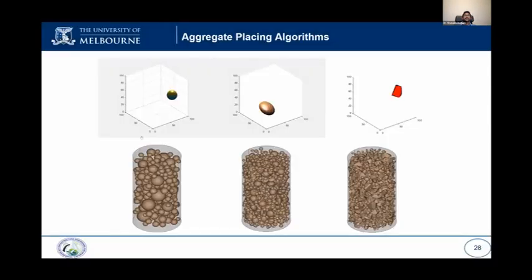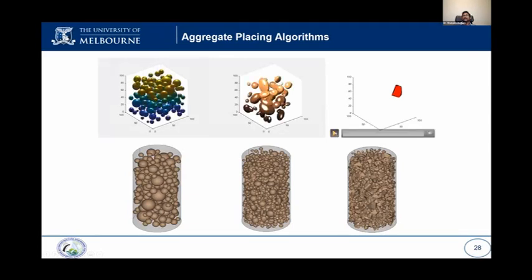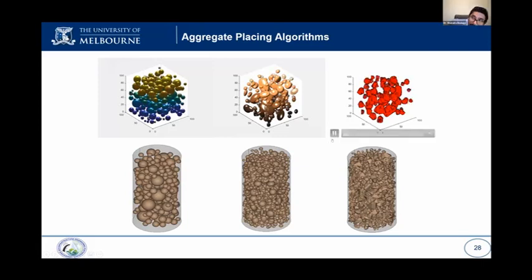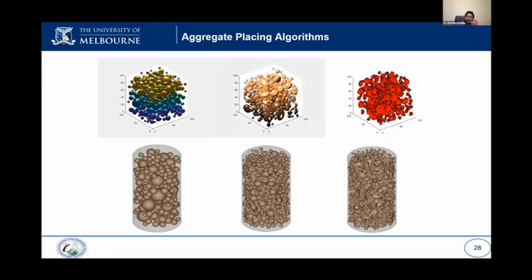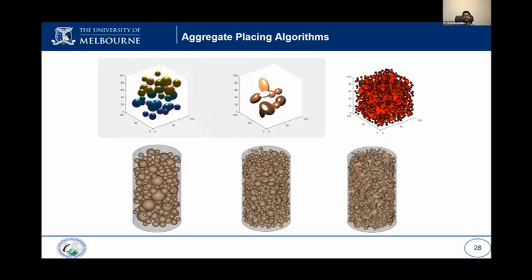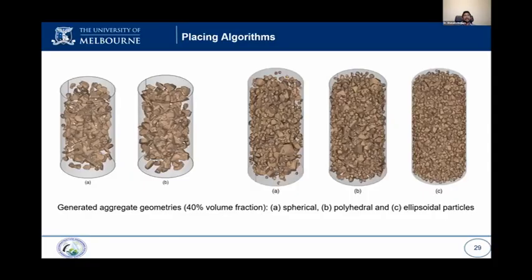So now it's about placing. I hope you can see the video. So this is the placing algorithm that Sadeep developed. He came up with his own algorithm. So one challenge in mesoscale modeling is placing the right amount of aggregate. Because of the current limitation, we can't place more than 30 to 35% aggregate. But with the new algorithm, we were able to place percentages of around 40%. So we achieved the right amount of aggregate using this algorithm.